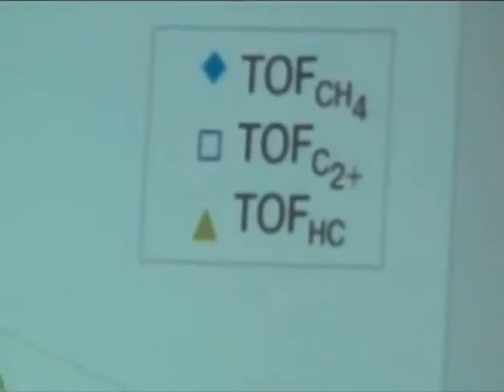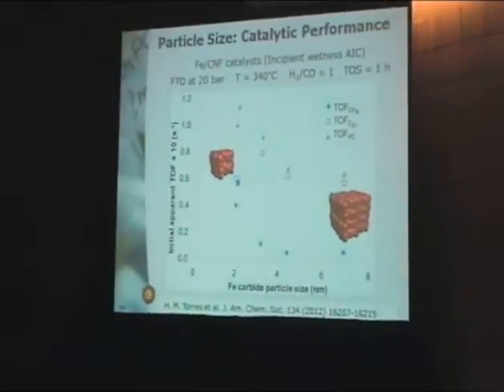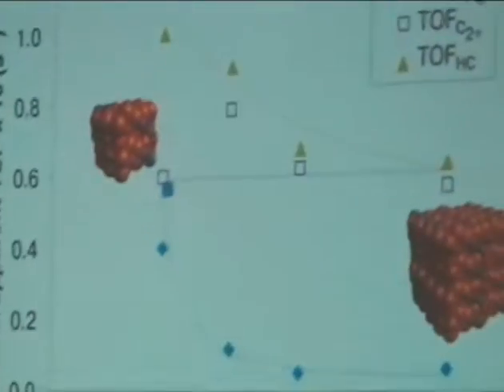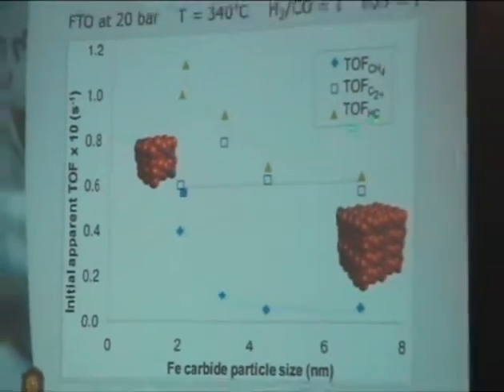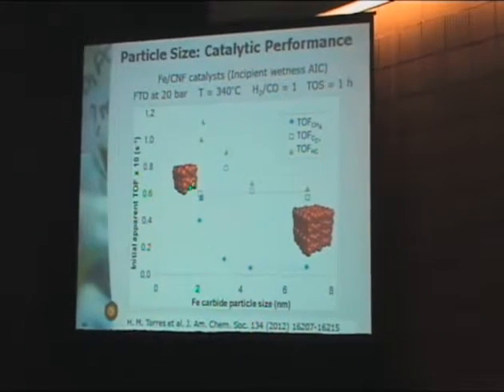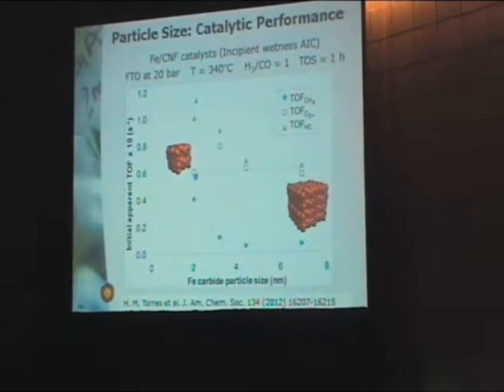The iron carbide particle size is very important. If we estimate or calculate a turnover frequency, which is much more difficult with iron, I would say, than with cobalt, or much less straightforward. But still, in an effort to do that, we have these numbers on the vertical axis and the iron carbide particle size. Using carbon nanofibers as support material, we observe an overall increase of the turnover frequency with decrease in particle size. This is very much the inverse of what we observe with cobalt. With cobalt it goes down, now it goes up.